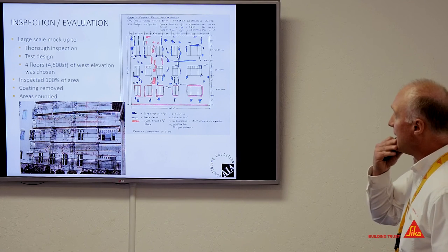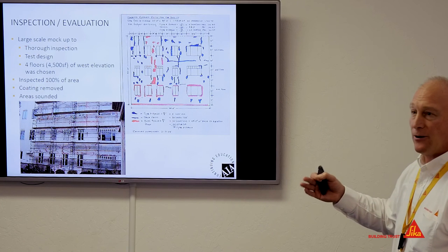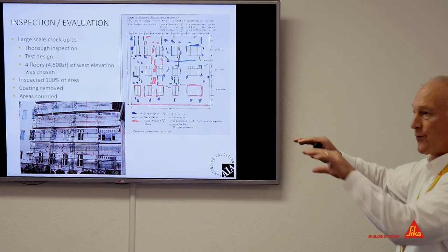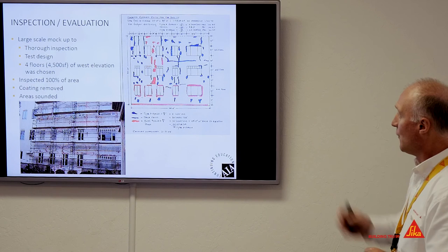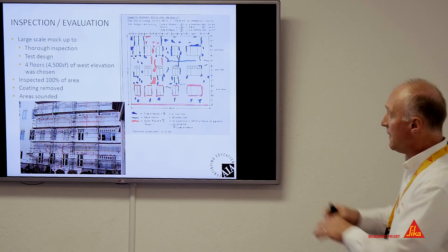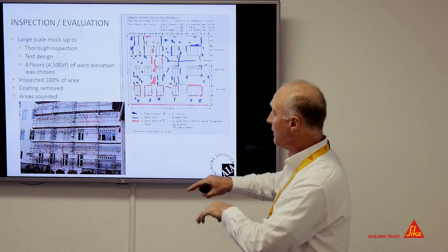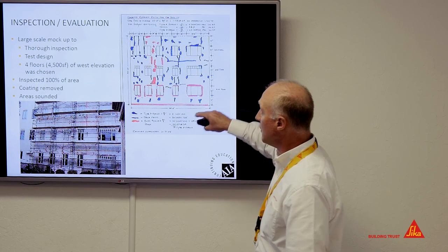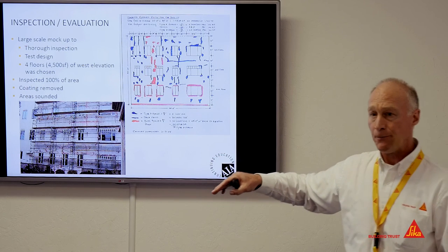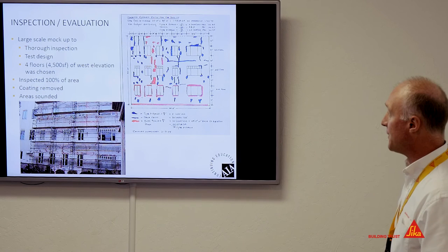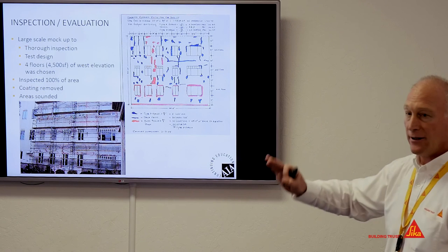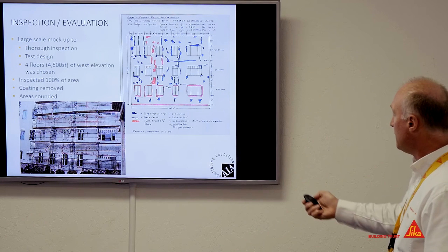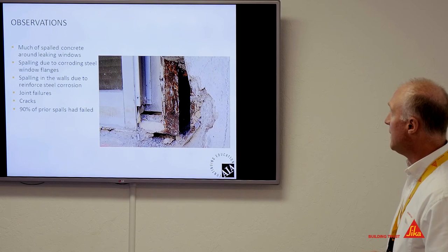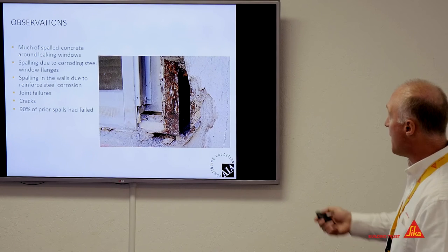In this case, the approach that they took is they did a very large mock-up. They picked about four floors on the western elevation, 4,500 square feet. They did 100% inspection of the area, came up with this drawing to identify the spalls. This is just during the mock-up phase, so they removed the coating, did all the sounding, and then the repair. A lot of the spalls were around the windows.